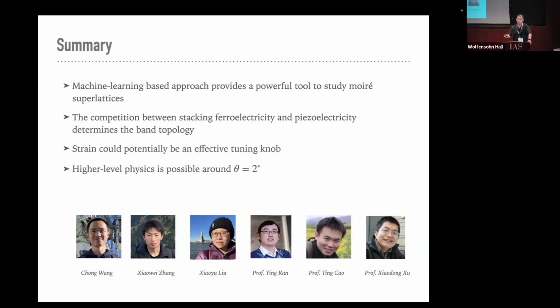Oh yeah, that's basically the whole point of that paper. One thing is simply to make the hopping smaller, as you said, right? But the other one is because of the d orbitals. If you think about dxy, dx squared minus y squared, they have very anisotropic shapes. So when you consider their hopping, the hopping itself is highly anisotropic. Even though the nominal t in front of it can be very large, because of this anisotropy the band can be made flat, as we showed. The band structure I showed there is just a very simple tight binding calculation. You put the d orbitals in there, and the flat band just comes out.